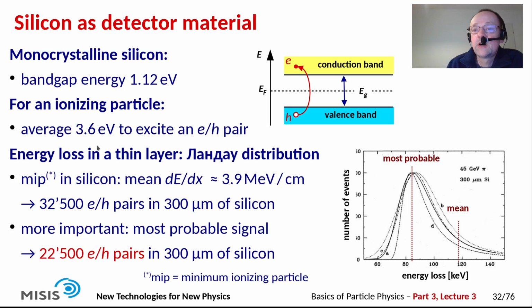The energy loss of an ionizing particle in our detector material is of course a statistical process, and for thin layers of material this is described by the famous Landau distribution that you see depicted here on the right. For a minimum ionizing particle, or MIP, in silicon, the mean energy loss is 3.9 MeV per centimeter, and this translates into 32,500 electron hole pairs created in 300 micrometer of silicon. And this is the typical thickness of a silicon detector that we would use in a tracking system.